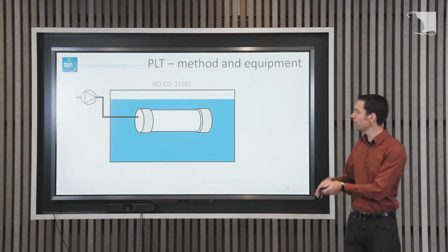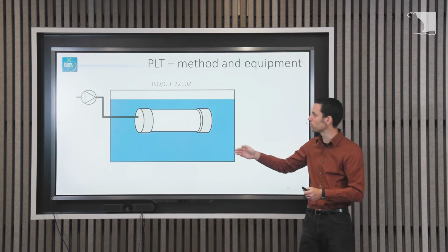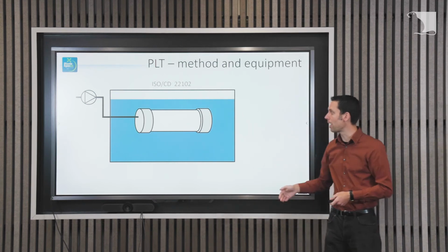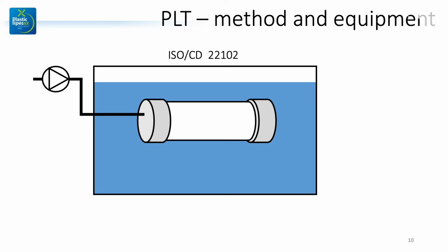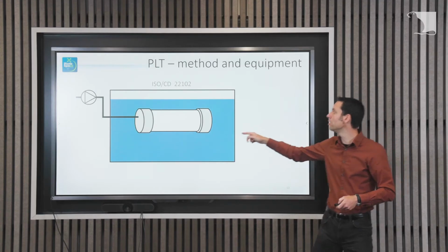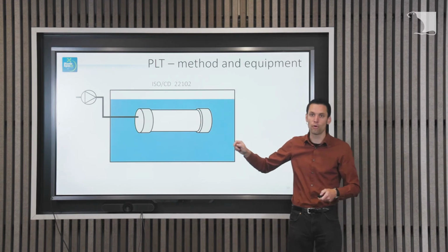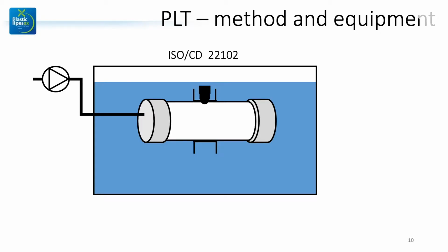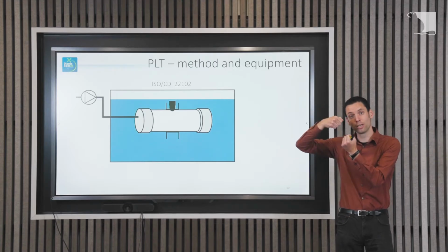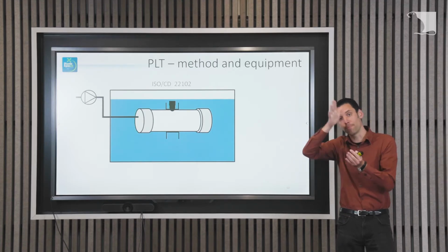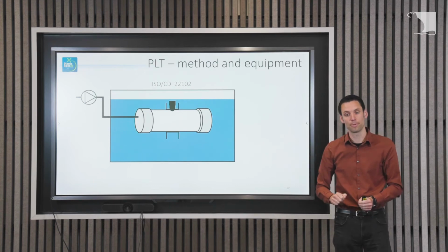So again, we have that polyethylene pipe, we have those end caps, we have a pump to pressurize the pipe, we have a water tank, which can be 80 or perhaps even 90 degrees. But in this case, we don't have any notches on the pipe itself. We have a point load. And on the other hand, a support, of course, otherwise you're just pressing the point inside the pipe and the pipe will bend. So you have to support the pipe.